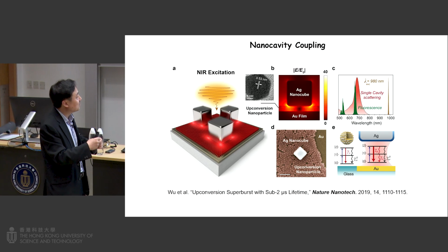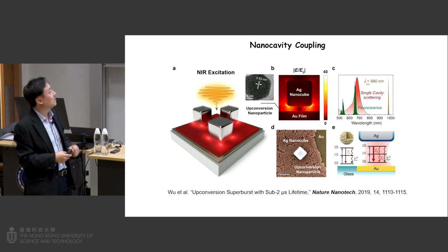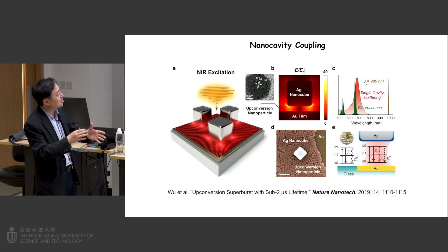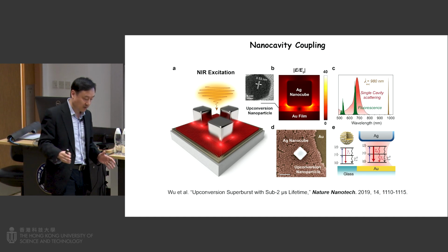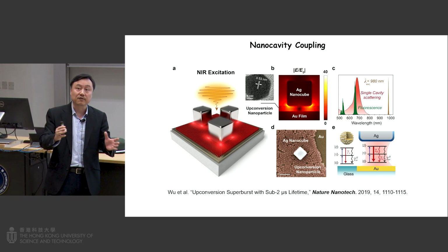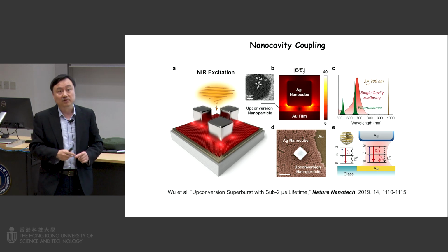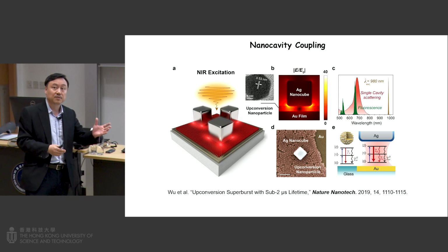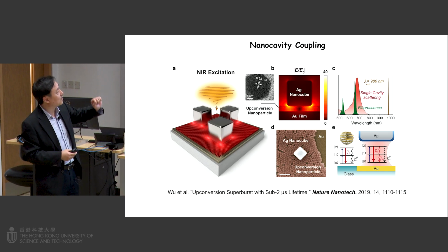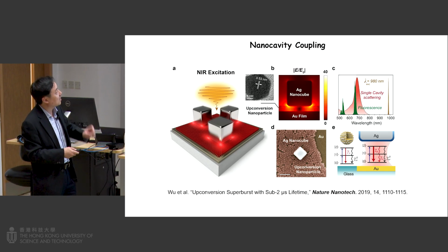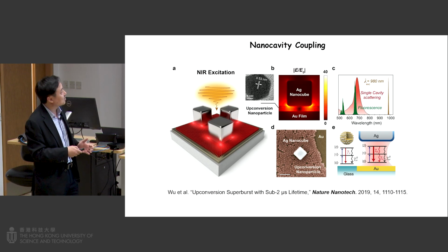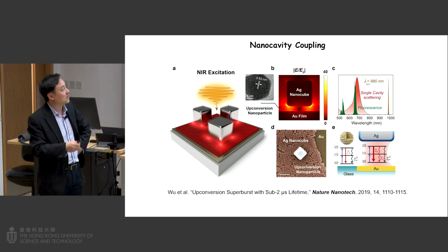I think there are interesting studies involving lanthanide ion upconversion. One challenge for upconversion, as I mentioned, is the efficiency. The quantum conversion efficiency is actually less than 1%. You compare that to organic dyes, quantum dots, which are almost much higher. So it's very, very low here. But how can we enhance that? One strategy is using the nanocavity. Here we showcase a sandwich structure: these upconversion nanoparticles sandwiched between a silver nanocube and a gold film, and you can achieve significant luminescence enhancement.